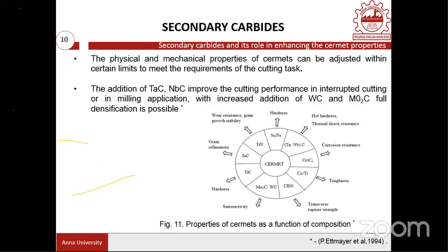So along with the titanium carbonitride, you can also add tantalum carbide and niobium carbide, if you are recommending this composition of the tool for milling application. So for interrupted cutting, you can add this tantalum carbide and niobium carbide, and the addition of tungsten carbide and molybdenum carbide, which act as a binder, will improve the densification. So this diagram represents the effect of different secondary carbide additions on the CERMETS.